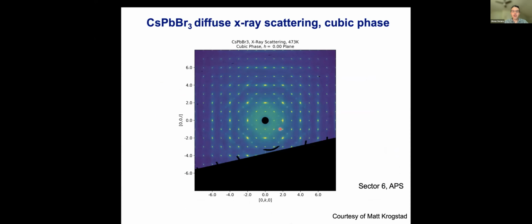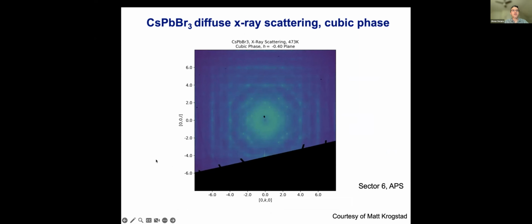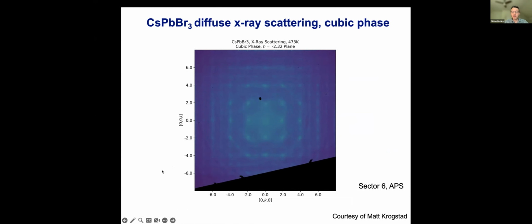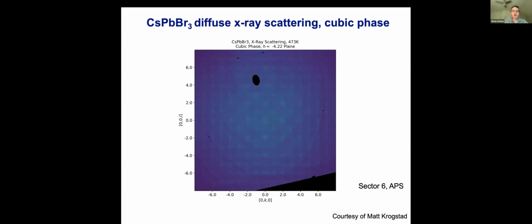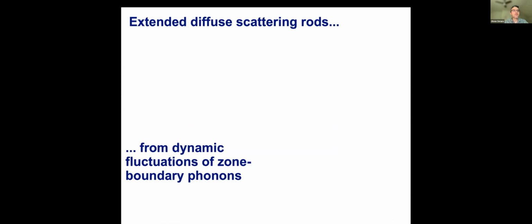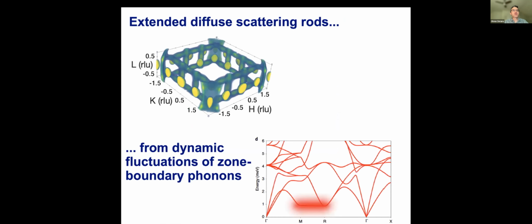All right. So quickly, let me show you, if I can get this to run here. The diffuse scattering is obtained from Sector 6. So we get these really nice volumes of reciprocal space here that show that in the planes that are half integer, we systematically see these beautiful rods of diffuse scattering here in between the integer planes where we see the Bragg peaks. All right, so we can take three-dimensional views. This is actually from the neutron data at the top here, and you see that indeed the diffuse scattering forms these rods. And so from doing the spectroscopy, as I'll show you in the next couple of slides, we can actually interpret this rod as coming from overdamped phonon modes along the edges of the Brillouin zone here.